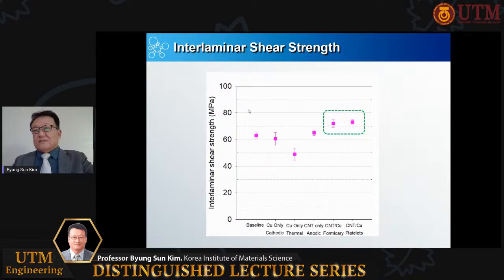The graph represents the interlaminar shear strength for various nanocomposites. Among all, the interlaminar shear strength is highest with both CNT copper formicary and CNT copper platelet nanocomposites. This may be due to the higher deposition of copper at CNT interfaces for CNT copper formicary nanocomposite and that of CNTs in the gaps between carbon fiber and the copper layers for CNT copper platelets.